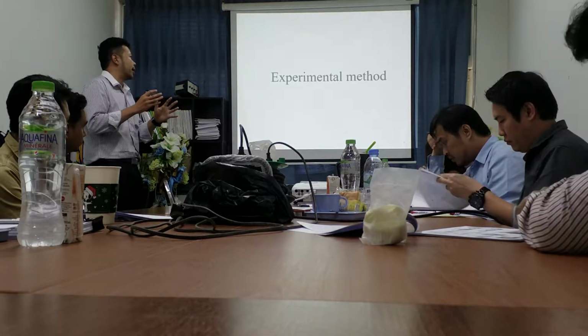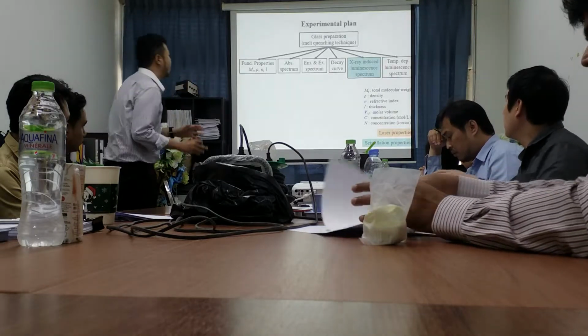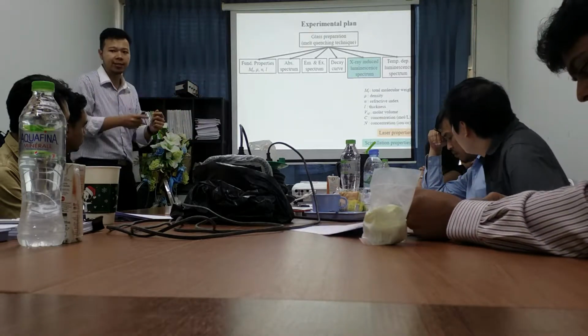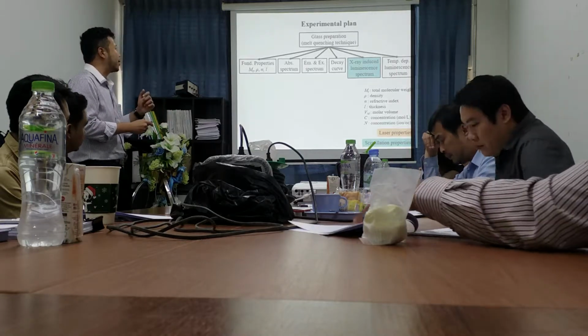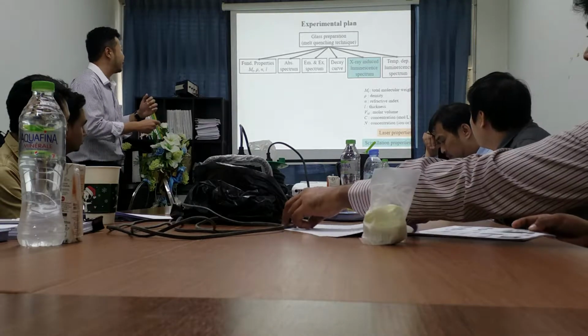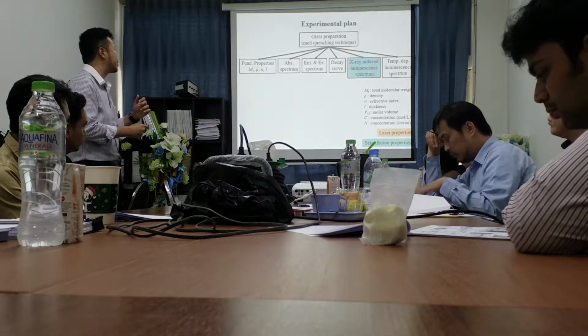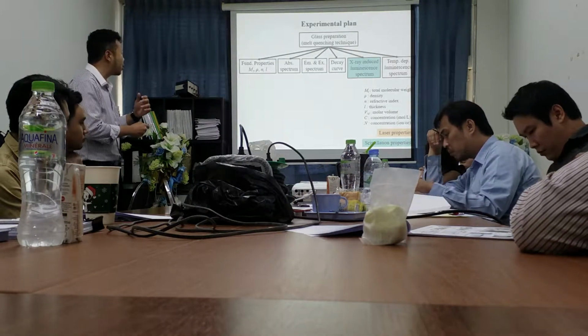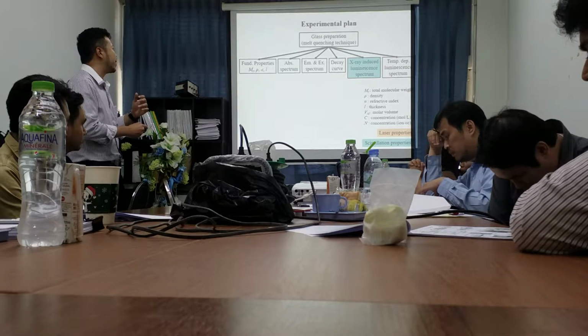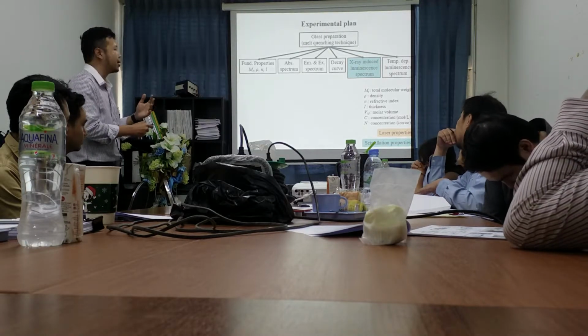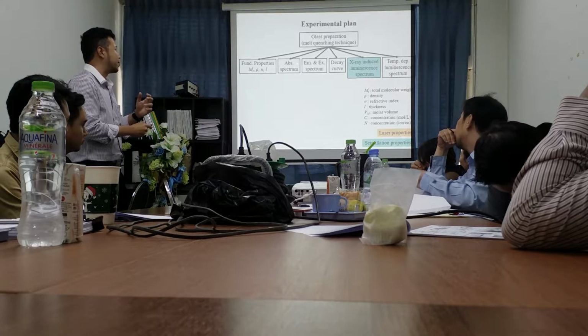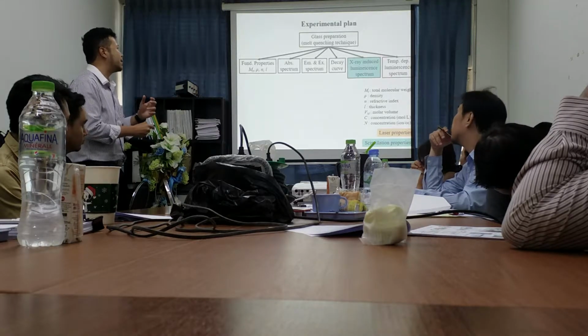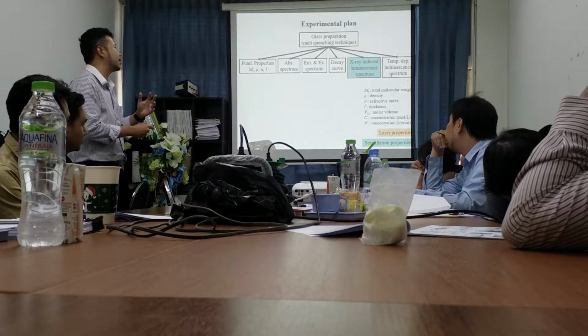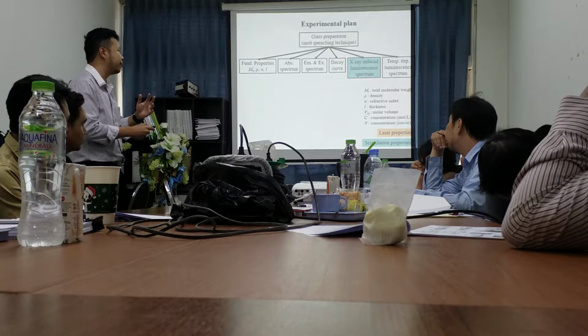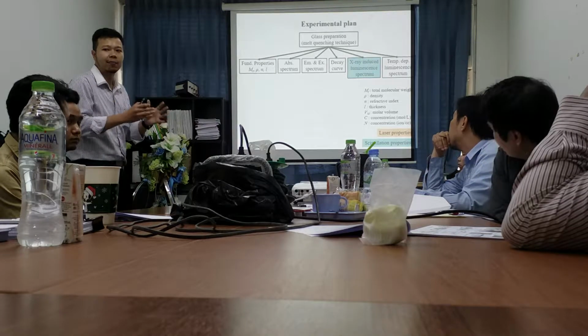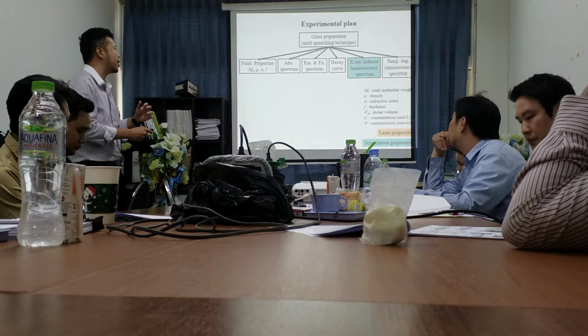Next, move on to the experimental method, starting from the whole process of this thesis. I prepare the glass by the melt quenching technique. After that, I study the fundamental properties by calculating and measuring the molecular weight, density, refractive index, and the thickness of the glass. I study the optical properties by the absorption spectrum, and investigate the luminescence properties by the emission and excitation spectra and the decay curve. I study the scintillation properties of the glass by measuring the X-ray luminescence spectrum.